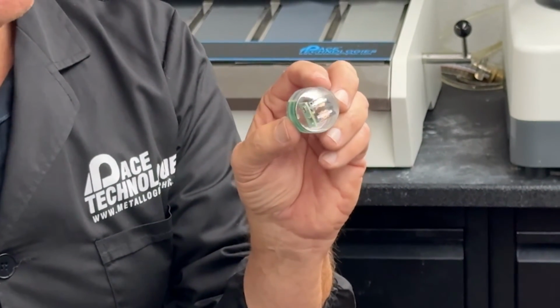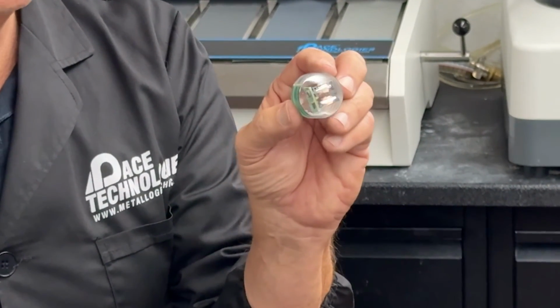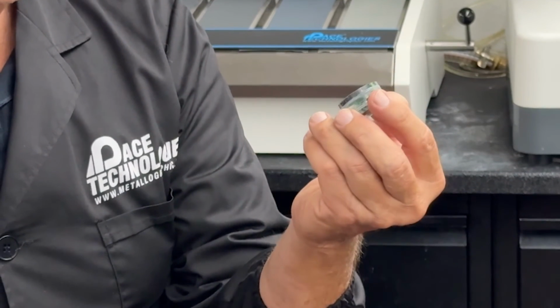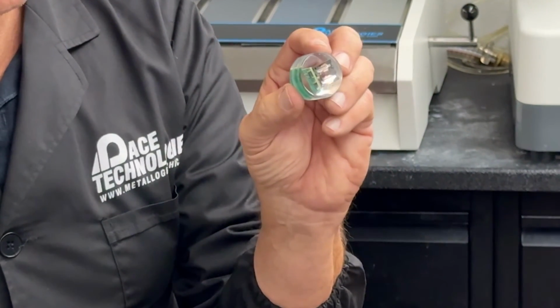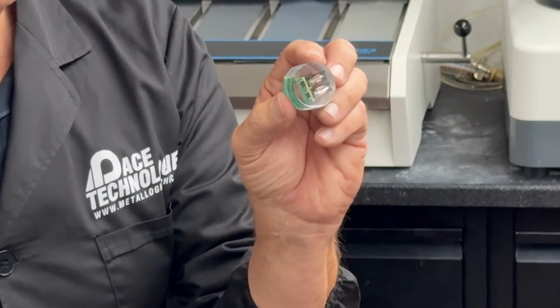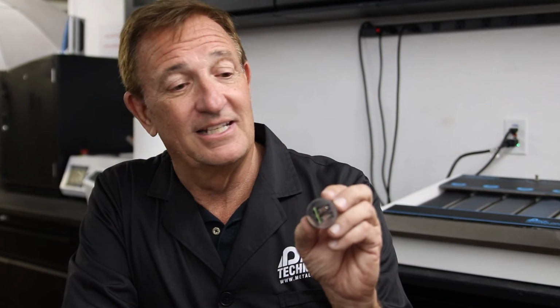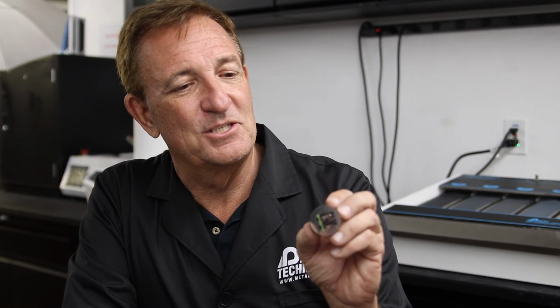So if we went to a polishing operation, we might deform those wires when we were polishing it. But by using vacuum impregnation, just visually looking at it, it looks like we did a very good job of supporting the internal structure of this sample. So it should make it a lot easier from our analysis point of view. Again, the ultra-thin, very nice, very, very clear.